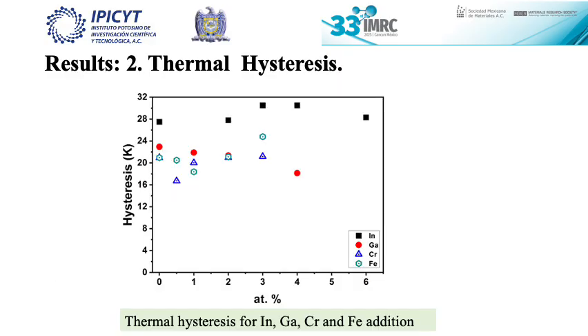For the case of thermal hysteresis, we can see that for the indium, the behavior is a little higher thermal hysteresis for the higher content of indium concentration. For the case of gallium, we can appreciate that decrease of this thermal hysteresis. For chromium and iron, we appreciate a slight decrease of hysteresis for the lower compositions.